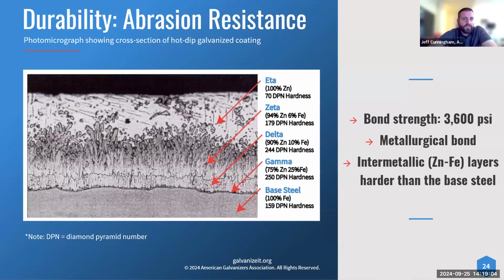So if you look at the gamma, delta, and zeta, first off, they're all a mixture of zinc and iron. Gamma is 75 zinc, 25 iron. Delta is 90-10, zeta 94-6. So you can see how they actually fuse together metallurgically. But then the DPN hardness number for all the gamma, delta, and zeta, all the alloy layers, is all above 159. So it's actually giving an abrasion resistance. It's actually harder than the base steel itself. So you also get that durability with the galvanized coating, as well as the longevity and corrosion protection.